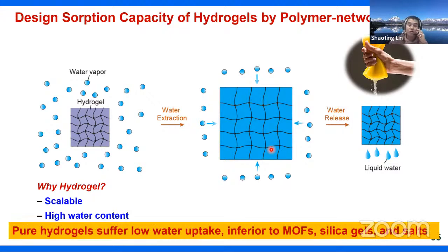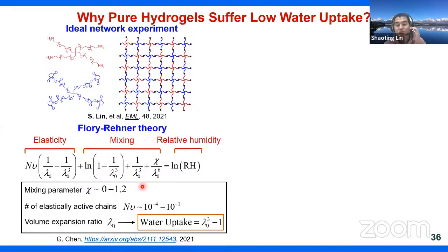What I would like to point out is that pure hydrogel suffers low water uptake. In fact, it is inferior to metal organic frameworks, silica gels, and salts. So I think this is something missing in the field. Let me first use an experimental theory to understand this. I use the ideal network, which is a material system free of molecular defects and containing monodispersed polymer chains. This is a very interesting material system for many interesting physics phenomena. If you're interested, you can check my recent papers.